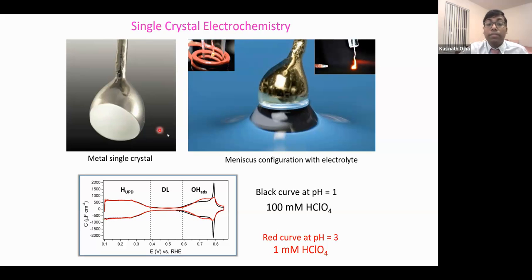You grow a crystal by zone refining, and then you cut it using a laser, right? No, not laser cutting. We cut by polishing with diamond. During that polishing we tune it, and in between we check how much angle we are getting using the laser. That's how we get those surfaces perfect.